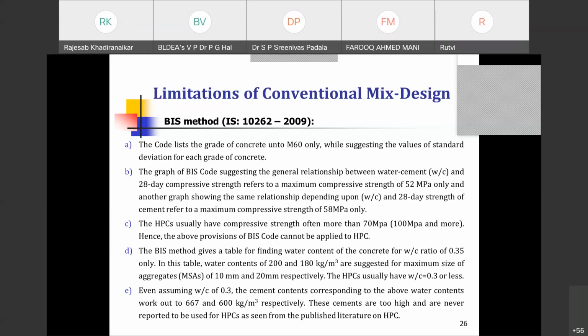But in some of the codes, what they do is, instead of standard deviation, they go for a reduction in the strength, divide it by some factor, and then increase the strength and design for that. But in our case, the standard deviation values are increasing as the strength is increasing.